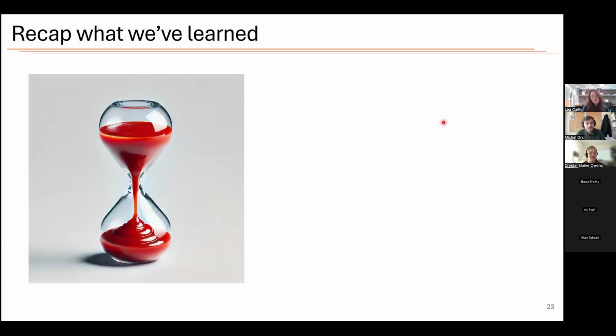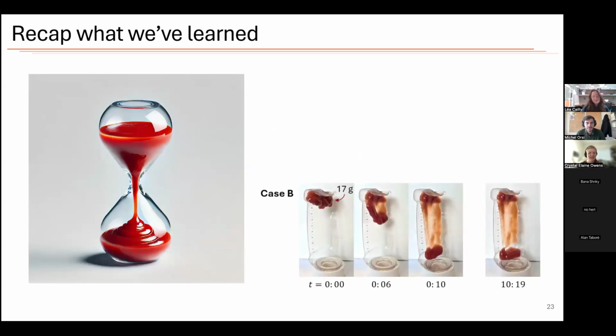So now we can recap what we've learned in the context of some of our tests. We had 2 cases that we saw before of what happens inside the bottle. Case B here is if you have a lot of ketchup, which has sufficient stress that it's probably able to shear internally. And so that's what's happening here: the ketchup has started to yield. There's a little bit of delayed yielding and then it falls down. So we have more or less understood that rheologically.